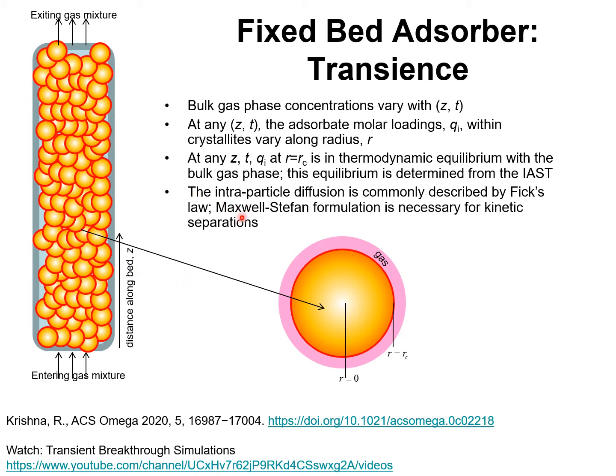At any z position and time t, the molar loading at position r equals r_c — the external surface of the spherical particle — is in thermodynamic equilibrium with the bulk gas phase mixture. This equilibrium is usually determined by use of the ideal adsorbed solution theory. The intraparticle diffusion is commonly described by Fick's law or the Maxwell-Stefan formulation, which is really necessary for use in kinetic separations.